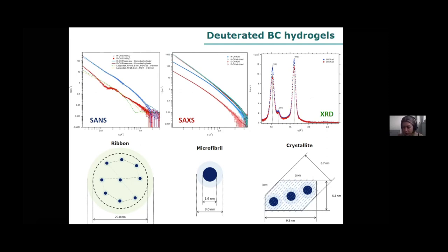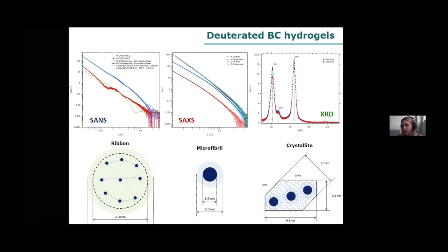The type of information we get from neutrons and X-rays is completely different. In the case of neutrons, we were getting information on the ribbon structure. In the case of X-rays, since we generated contrast between crystalline and amorphous domains, we got structural information on the cellulose microfibrils. It is also advisable, if you have semi-crystalline carbohydrates, to do some X-ray diffraction, as that will also help a lot. I think I will finish here — you can check on the other examples later on, and since we have 10 minutes for questions, please ask anything you want.